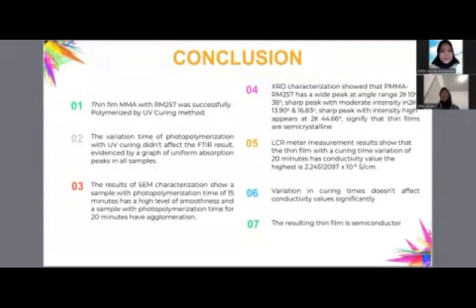Fifth, LCR measurement results show that the thin film with a curing time variation of 20 minutes has the highest conductivity value. Sixth, variation in curing time doesn't affect conductivity value significantly. Seventh, the resulting thin film is a semiconductor.